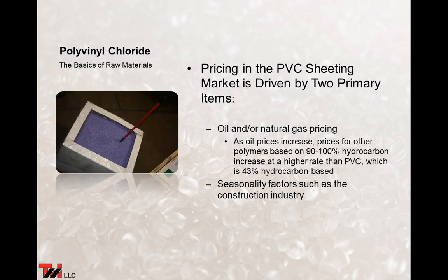I mentioned pricing in the PVC sheeting market. It's driven by two primary items, oil and or natural gas pricing. Even though most of the PVC resin in this country is made using natural gas, oil still is one of the big drivers. If you watch the pricing of oil, you can see what is going to happen to the cost of PVC. The PVC manufacturers still tend to follow the oil prices. As oil prices increase, prices for other polymers based on 90 to 100% hydrocarbon, and we're talking about polypropylene, polyethylene, some of the other polymers, they increase at a higher rate than PVC because PVC is 43% hydrocarbon based. So a lot lower usage of oil and or natural gas in the manufacture of PVC resin.